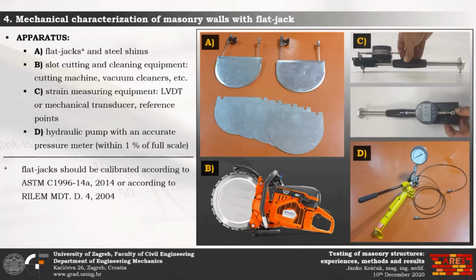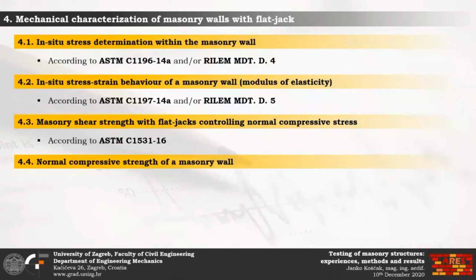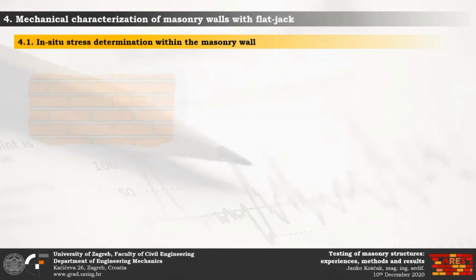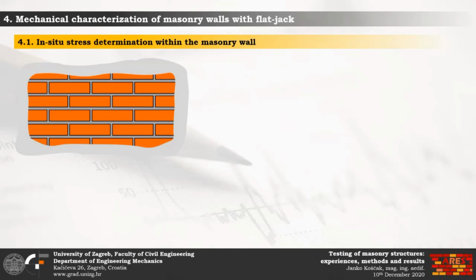Apart from the flat jacks, steel shims are needed in order to compensate for the gap width between the slot and also to protect the flat jack from damage. Secondly, the slot cutting and cleaning equipment is needed, and strain measuring equipment is also necessary, such as LVDT or mechanical strain transducers, as well as the reference points which are attached to the wall. Finally, the flat jack has to be connected to the hydraulic pump equipped with the pressure meter. The summarized test procedures for the various mechanical properties that can be obtained with the flat jacks are shown in advance. Firstly, in situ stress determination within the masonry is described here.